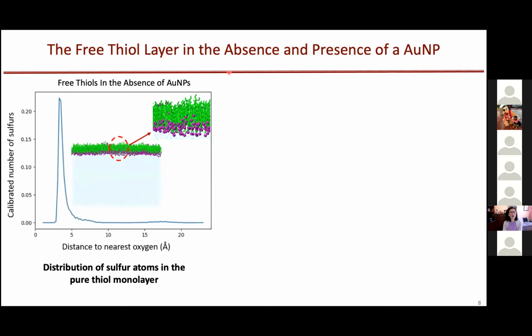Lindsay's simulation also shows something interesting about the structure of the free thiol layer at the interface, with and without the gold nanoparticles. Without the gold nanoparticles, the free thiols behave just like surfactants, forming uniform monolayers with the sulfur atoms anchored at the air-water interface.